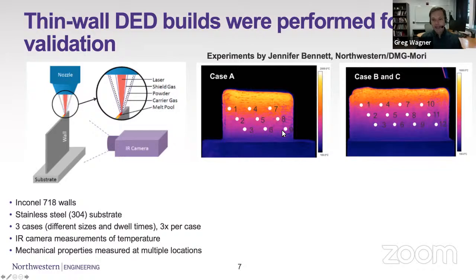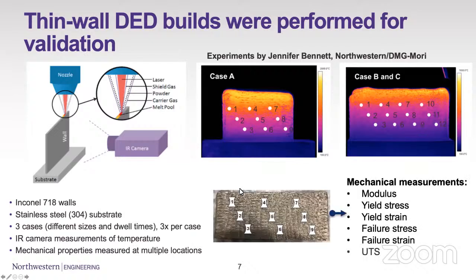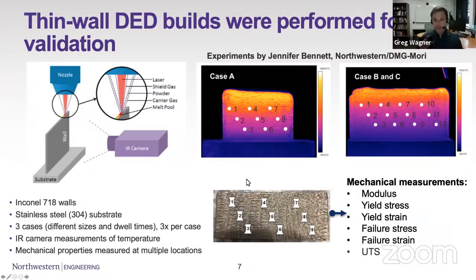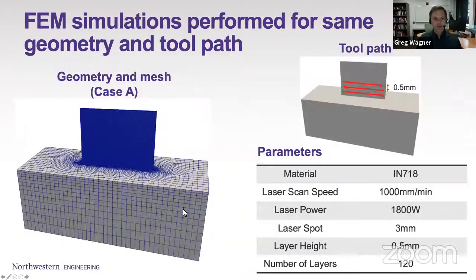Each one of these walls had a number of sample points, either 9 or 12, depending on the size of the wall. In addition, we were able to take sample specimens from these walls and measure the mechanical properties, things like the elastic modulus. With tensile tests, we got the stress and strain at yield and failure. And UTS is one that I'll show in a few cases here, the ultimate tensile stress. So we have a number of points where we have IR data that purports to give us a measured temperature field. We have property data at those same points.